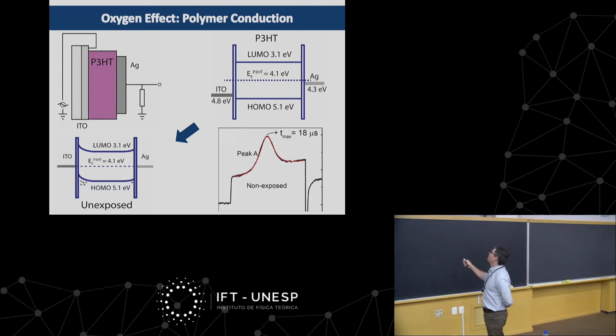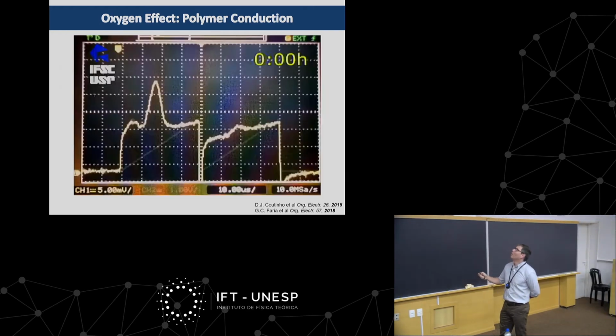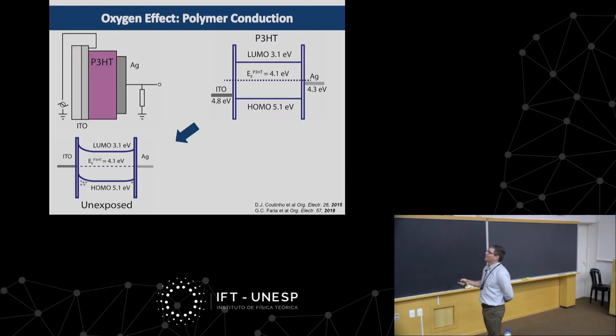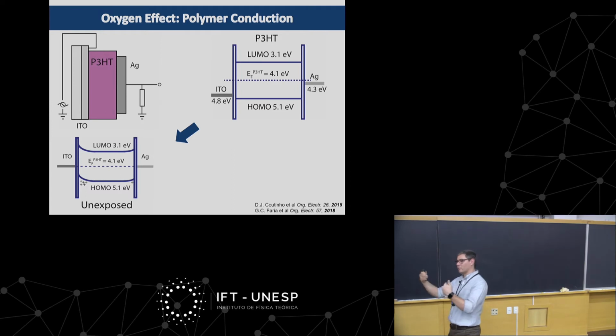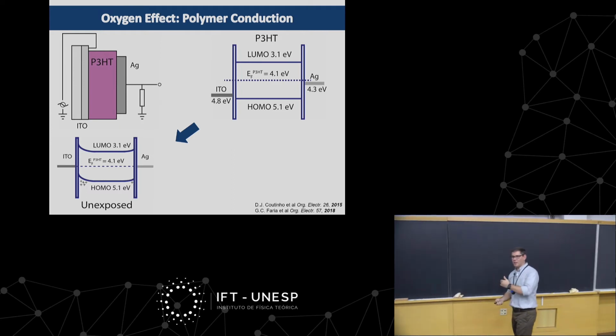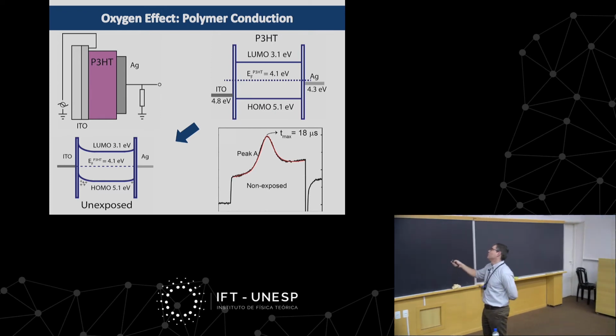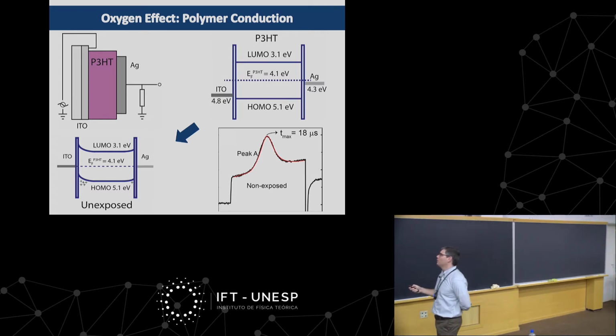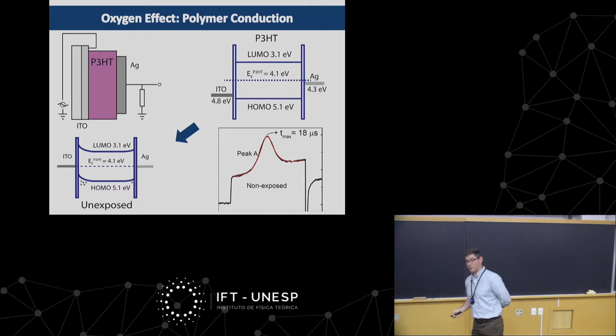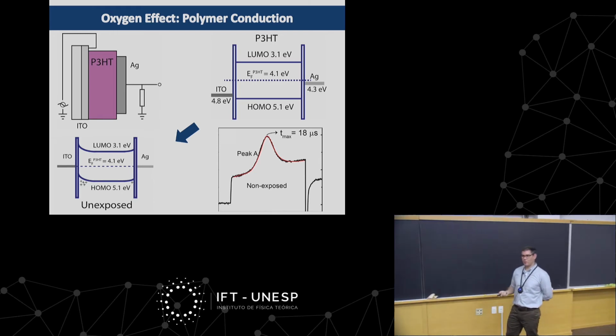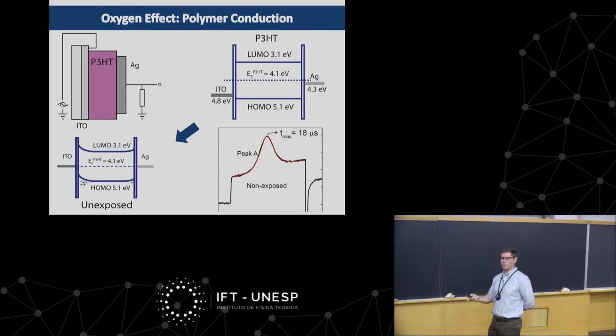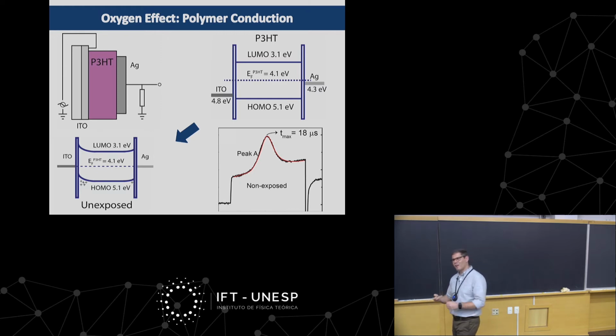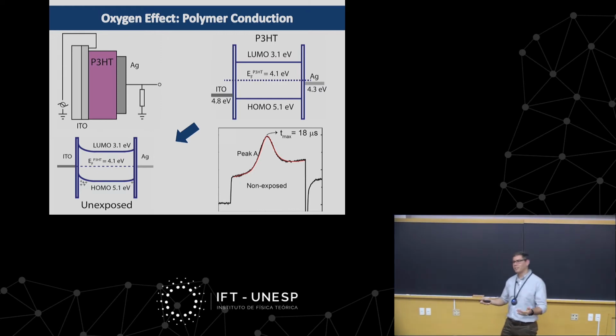And therefore, that first peak that we saw initially on the non-exposed device was actually attributed to the extraction of that reservoir of charge lying at the interface for, of course, energy equalization at that interface. So this is the reason for the non-exposed device. And actually, this is quite important for the field because we all knew that those charges were there. But this is the first time a measurement was capable of accessing that type of charge because you create a image-charge interaction here. So it's very hard to really use techniques to access those charges.